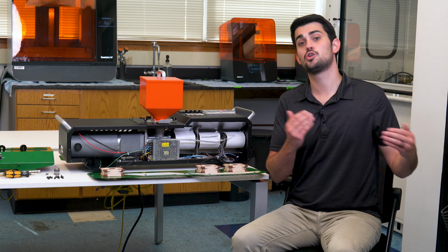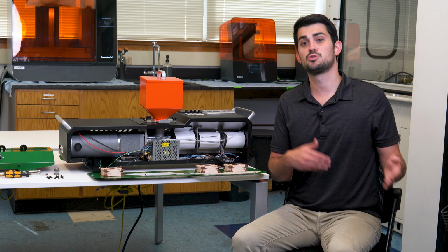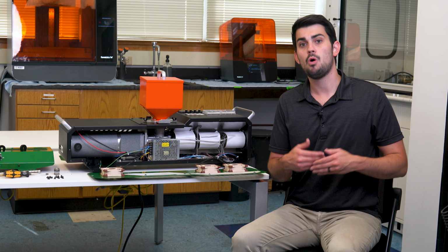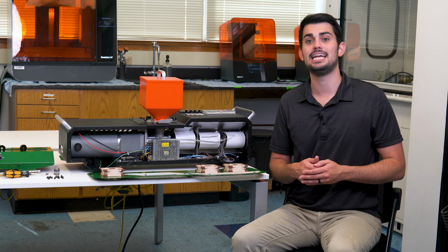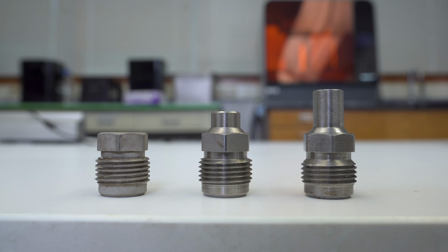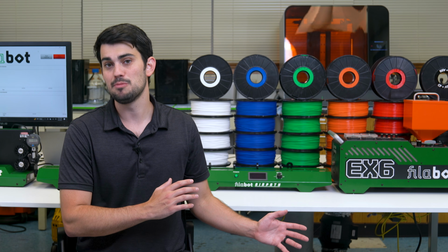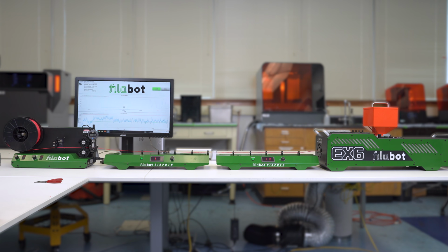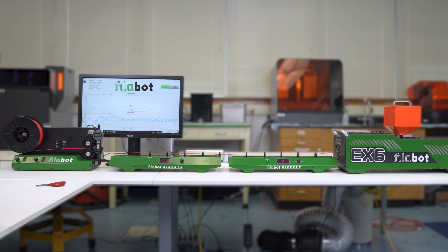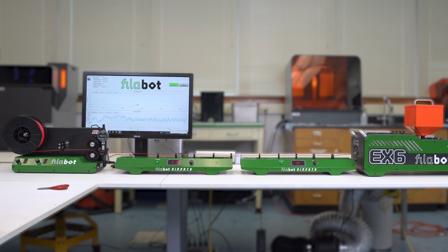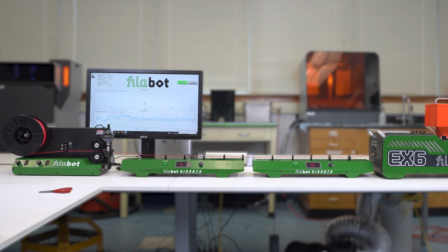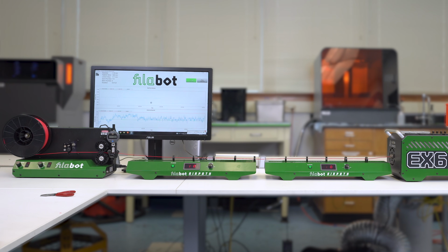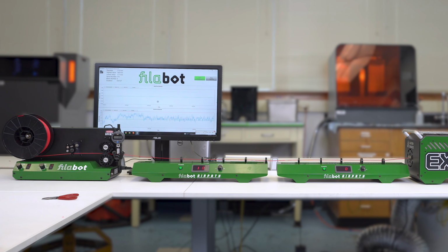Higher RPM will increase the average melt temperature of the polymer, which will require more cooling after extrusion, or may not have a high enough viscosity to maintain its shape when leaving the die. A longer die, as discussed previously, can combat this, which is known as extruder drool. Filabot claims that the EX6 is capable of 4.5 kilograms or 10 pounds per hour of output, but this is largely dependent on the setup of the machine, the plastic being processed, and the amount of cooling on the other side of the die. With my conservative general purpose setup and 2 air paths, I see closer to 2 kilograms per hour when extruding PLA.